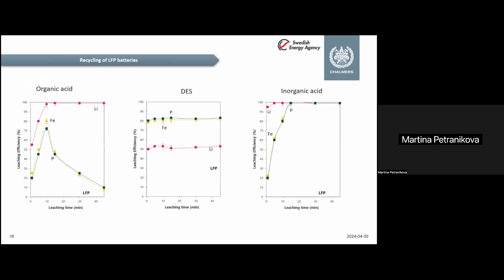We have also been working quite a bit on the recycling of LFP, using organic acid, and also deep eutectic solvents and inorganic acids. Unfortunately, this research hasn't been published yet, so I cannot share which organic acid, deep eutectic solvents or inorganic acids we have been using. But what is interesting is that with the organic acid we achieved a very nice separation of lithium and iron over time. That could be one way the lithium could be selectively recovered from the system, while the iron and phosphorus stay in the solution.